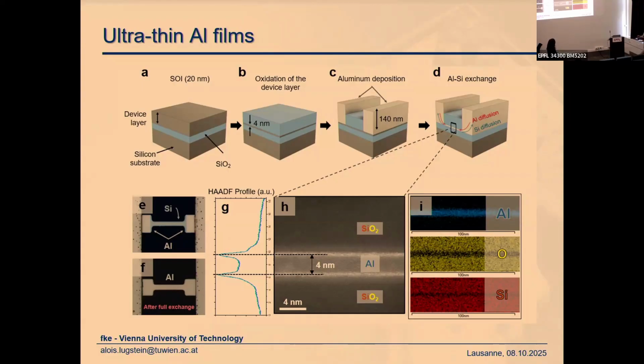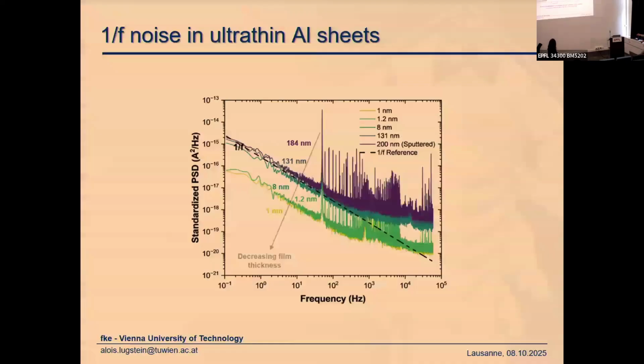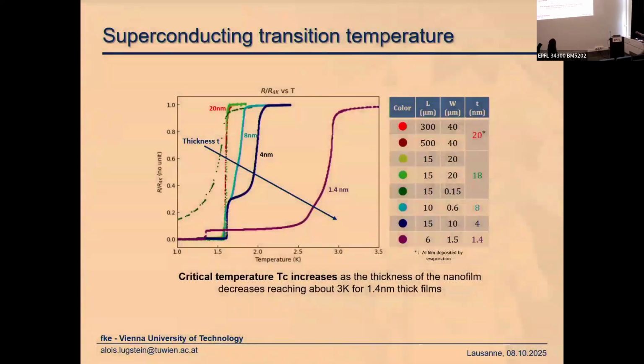If you make a 1 nanometer thick aluminum sheet, you can do it in an MBE system, but if you take it out, it's immediately oxidized. These devices are stable; we made them a year ago. This is 4 nanometer, measured by ellipsometry. Finally, we send it to cooperating partners for TEM, and the thinnest one is now 1.4 nanometers. That is now also proven by TEM.